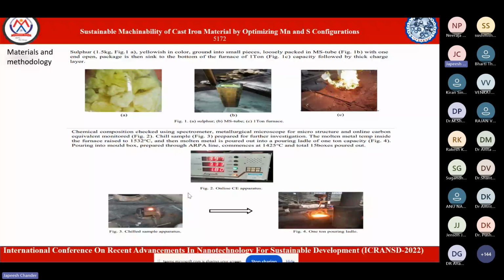We make a hearth. If you see on the right side, this is a melting furnace. This is medicinal sulfur, almost pure sulfur. We pack this pure sulfur into a tube, sealed at the bottom side, with a thickness of around 5 mm all around. We kept the top side open. We just fixed it with a small plate without sealing it properly, because when sulfur gets heated through the walls of the metal, it will become a gas and it can explode. So to avoid that, we kept a small opening at the top.